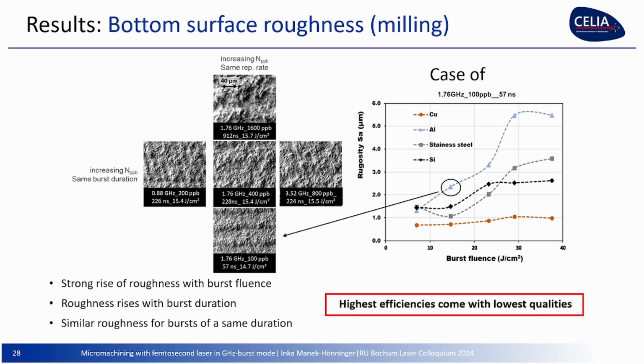What about cavity milling? Cavity milling, well, as you can see here, there's quite a strong rise of the roughness with the burst fluence. So when you increase the burst fluence, unfortunately, the surface roughness increases as well. So here the highest efficiencies come with the lowest qualities. You cannot have everything.